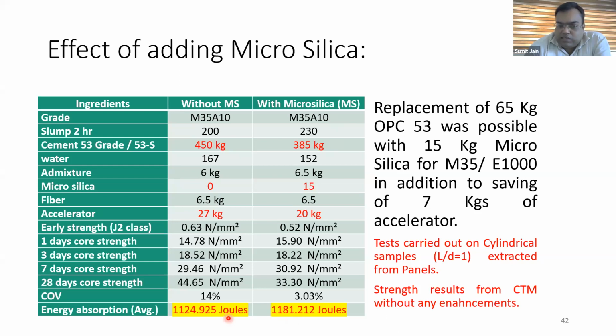So this clearly establishes that adding microsilica actually enhances the durability of the Shotcrete. Because of a good mix in the hardened state, the fibers are really playing their role. And even the COV, the coefficient of variation, was very less. It was only 3%. So we were able to replace 65 kgs of OPC by adding just 15 kgs of microsilica. And this corresponded to M35 E 1000 joules.